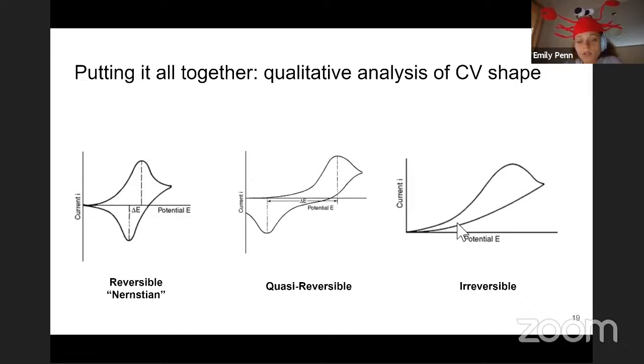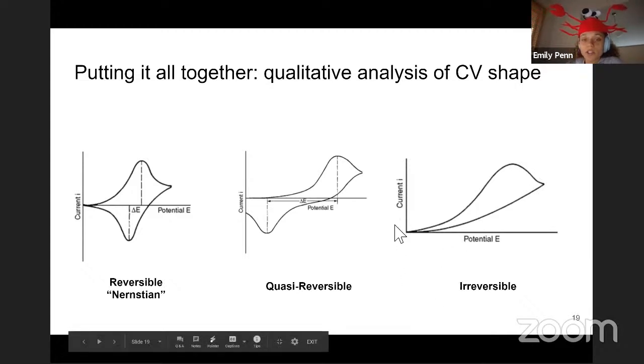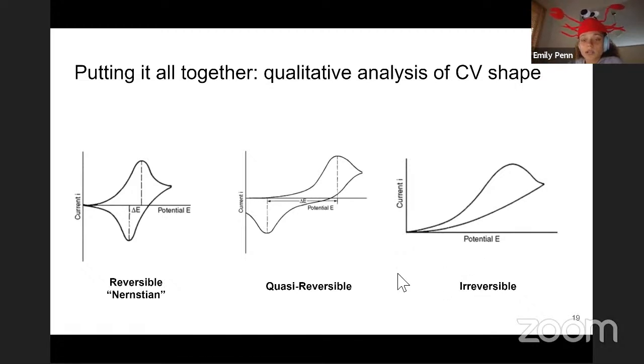For an irreversible system, here we see a really irreversible system where we only have a peak in one direction. So we're able to form the oxidized species, but then we're not able to go back and reduce it. So there's no reverse peak on the reverse of this scan. That would indicate that you have a reaction that's irreversible.